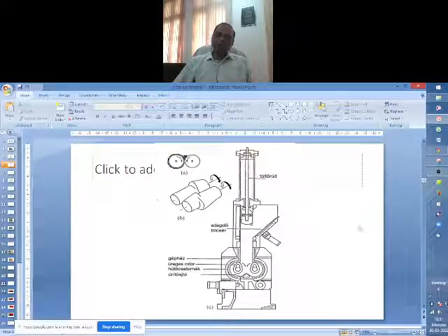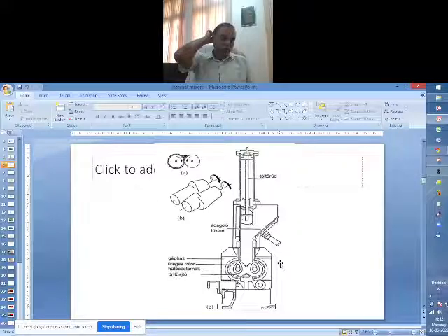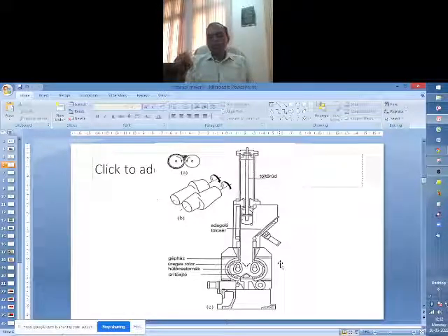Ram up, zero time. If you imagine, the feeding happens in 10 or 15 seconds. Then you say ram down. The rotor is continuously running. After 30 seconds, ram up a little bit, and the ram pressure will be eased. Then again ram down. This is for improving the mix quality. This way, you define the operational protocol: what time the ram will be down, what breathing time will be given, what time the full pressure will be applied, how long it is kept in the system, at what RPM, and at what time it will be dumped.